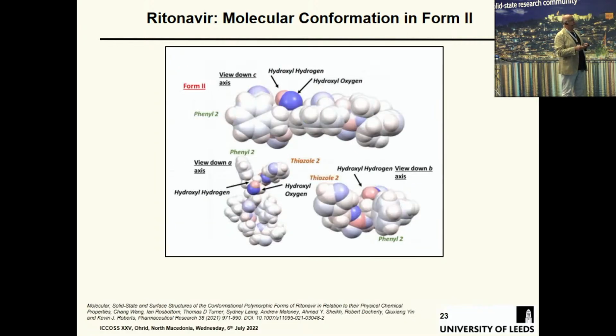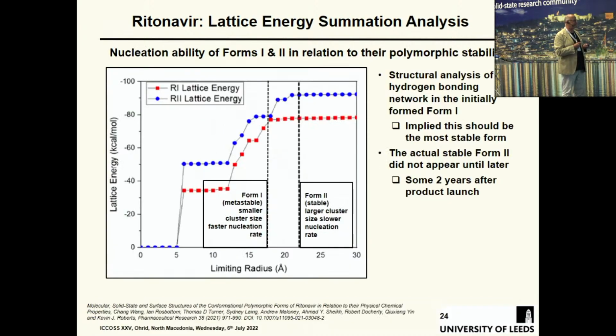If you look at form 2, it's a lot more available as a structure, and in the form 2 conformation, you can see that you can get to both the hydroxyl oxygen and the hydroxyl hydrogen, and that was the missing link. They thought they had satisfied all the hydrogen bonds, but they didn't realize the importance of the hydroxyl oxygen as a hydrogen bond acceptor. Arguably, they should have, I would think even 20 years ago.